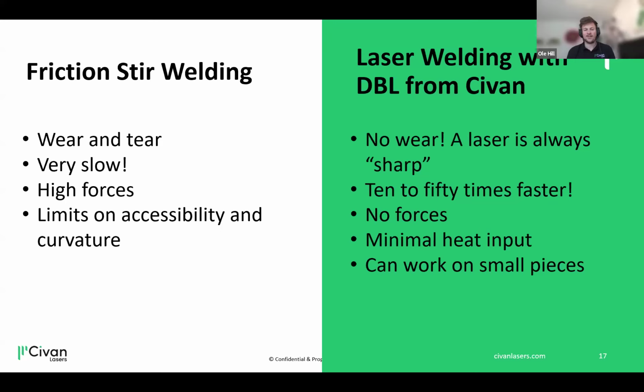And well, the laser welding has a lot of advantages compared to friction stir welding. One of these is that the laser is always sharp. You don't have any wear and tear on the laser at all. So you can rely on it to work the same as yesterday and last week and last month, as long as you have control over the rest of the system, the laser will perform in the same predictable way. As I mentioned, it's magnitudes faster, and also no direct forces are applied to the part, only forces indirectly by cooling gradients. But you have those with any kind of welding, so I wouldn't say that's specific to laser welding.